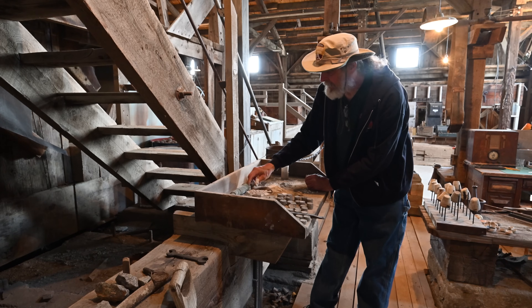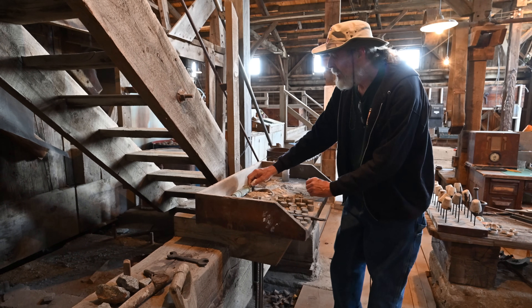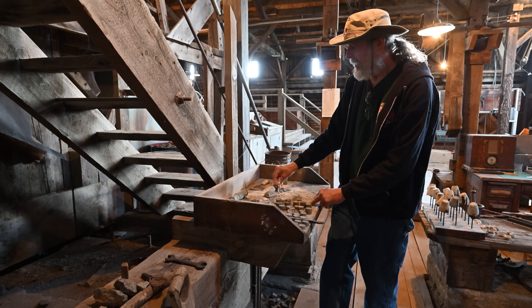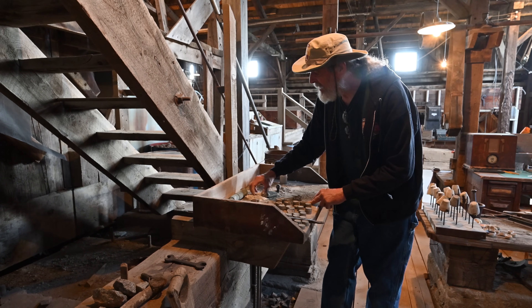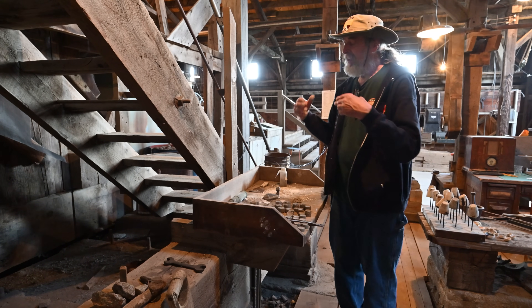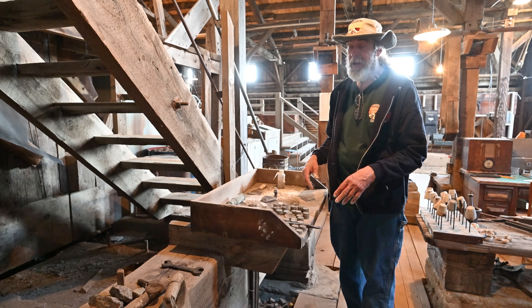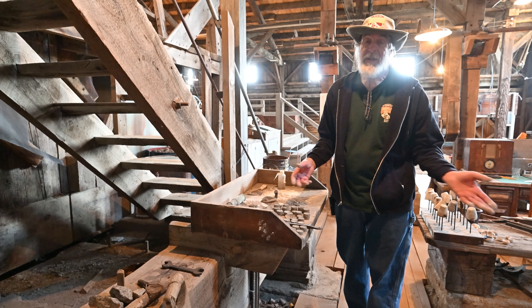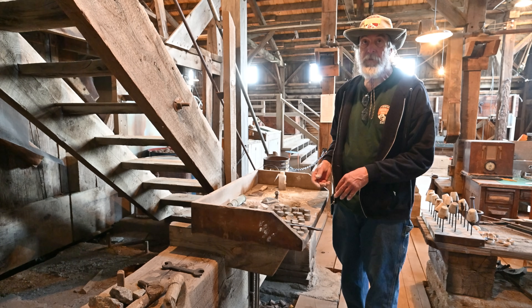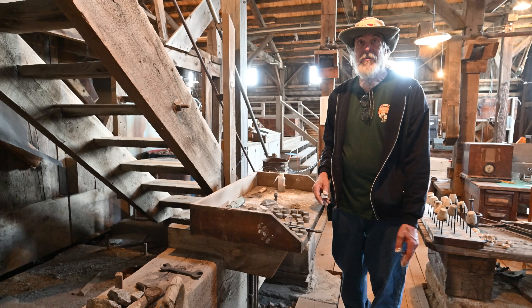You shut the lid, then step on the lever and put all your weight on it, open the lid, and your cupel pops out — looks like that. You could make 200, or if you were good at it, up to 400 in an hour. All of the lower-ranking assayers or the helpers would have to make cupels every day. You let them dry for a week and they're ready to go.